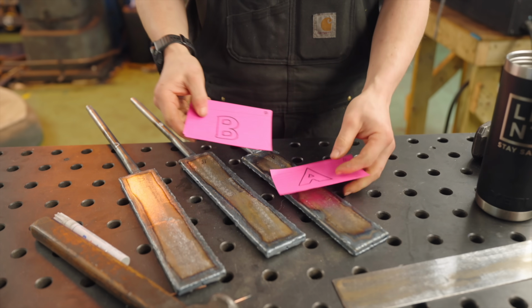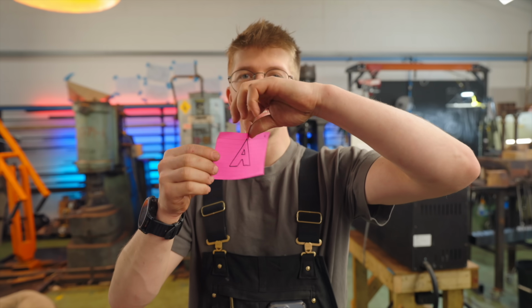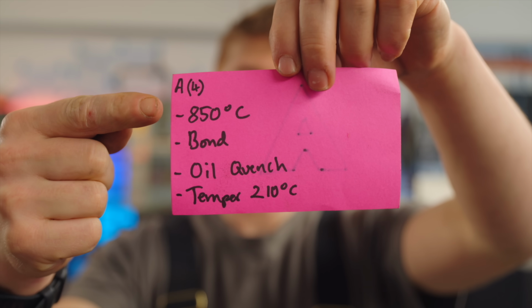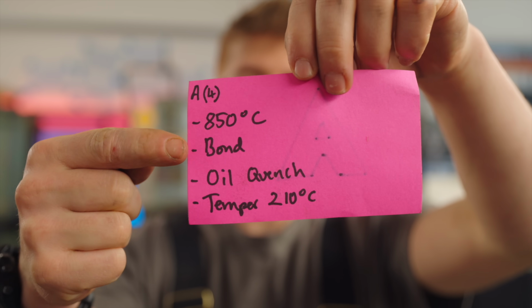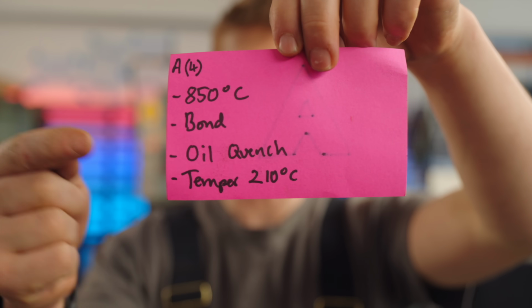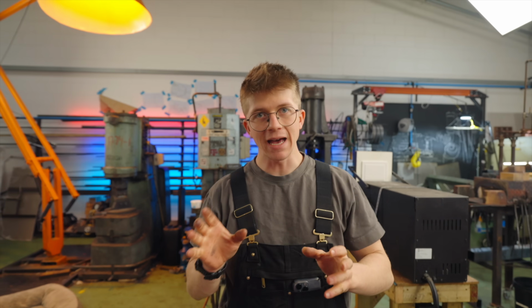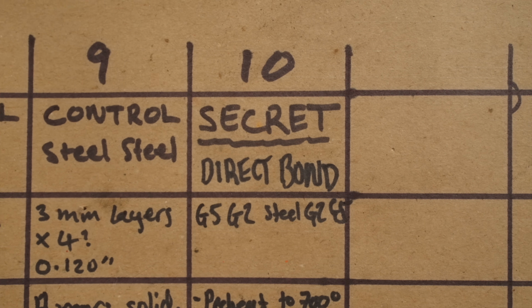So now I present to you a little CBA. Billet A is going to go like this. We're going to heat it to 850 degrees Celsius, smash it under the steam hammer to bond it, immediately oil quench it, and then temper it at 210 degrees Celsius. Now that is going to provide, hopefully, an identical result to our previous experiment's famous secret sample.